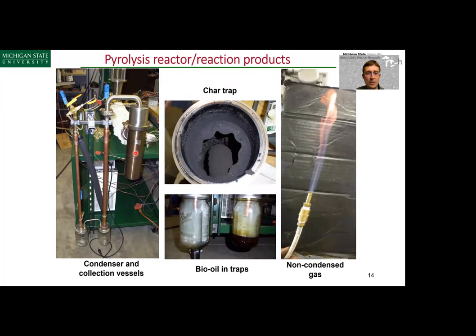Looking down the biochar trap, if we take the top off, you can see that we collect biochar there, and we typically get yields as low as 12 weight% and as high as 25 weight% in this particular device. And the non-condensed gas is combustible, as you can see here.